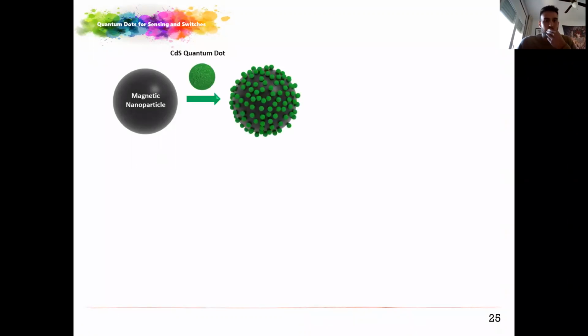Moving to a project from my group, I'm currently working on a new sensor also using quantum dots. For that, I'm using magnetic nanoparticles decorated with quantum dots on the surface. And after the incorporation of beta cyclodextrin, which is a molecule that can discriminate analytes depending on the size of these analytes,